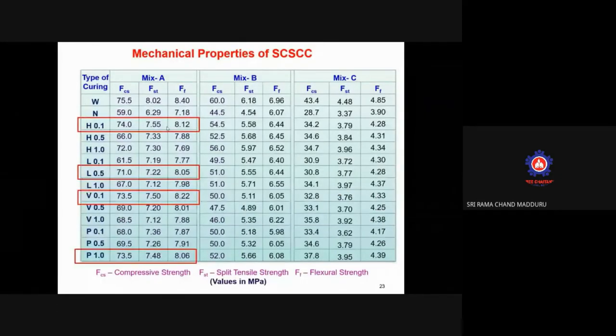So for every particular self-curing chemical, there will be an optimum dosage, which can be obtained with respect to research study. From the research study, with the availability of material, this dosage of self-curing chemical will differ. And you can observe W is nothing but water curing, N is nothing but no curing. When I cure the concrete, we will achieve 75 MPa. But when you don't cure the concrete, there is a reduction in the compressive strength, which is 59 MPa. But if you add self-curing chemicals, on par with the water curing, we are getting the required strengths. This is observed for high strength and standard strength concretes.